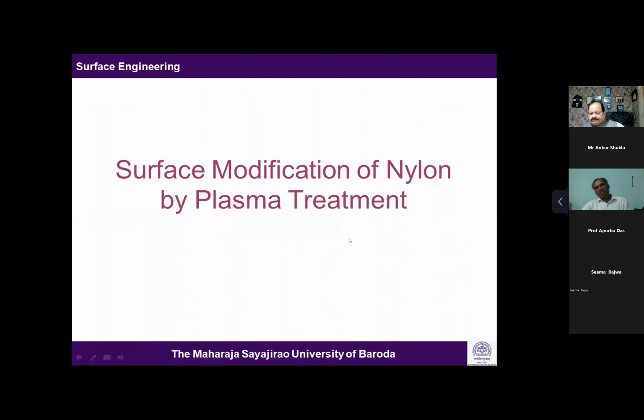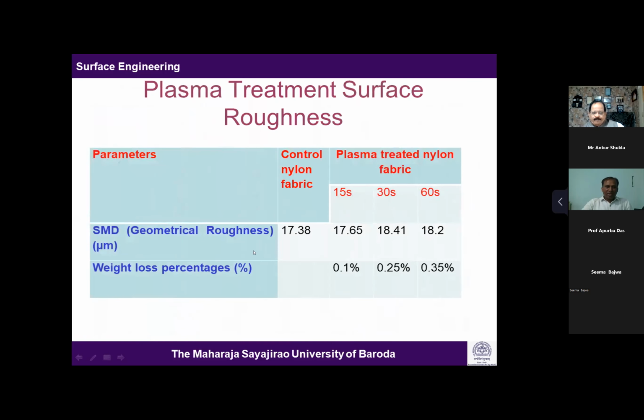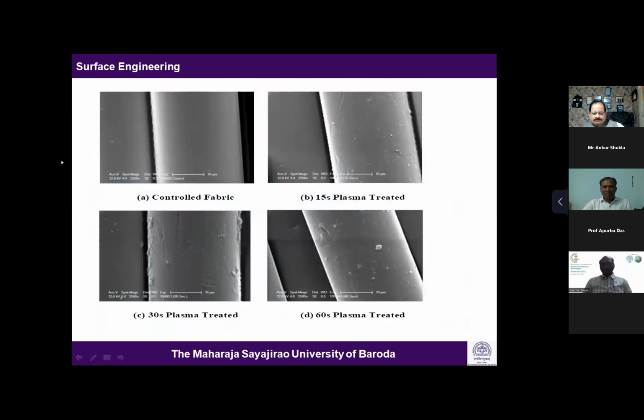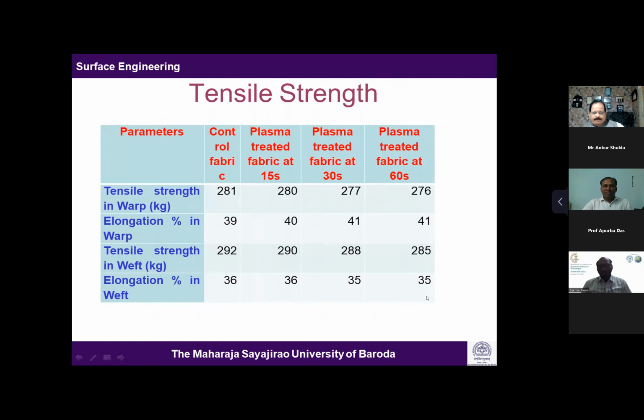The next thing we did was with plasma. We did the treatment for 15 seconds to 60 seconds, and there is an increase in the surface roughness. The weight loss is very low because the plasma is restricted to the surface only. These are the plasma treated nylon samples. In tensile strength, we see a slight decrease here also, but not much. It comes down to 292 and 290 only at 15 seconds, and with 60 seconds we see a slightly lower value.